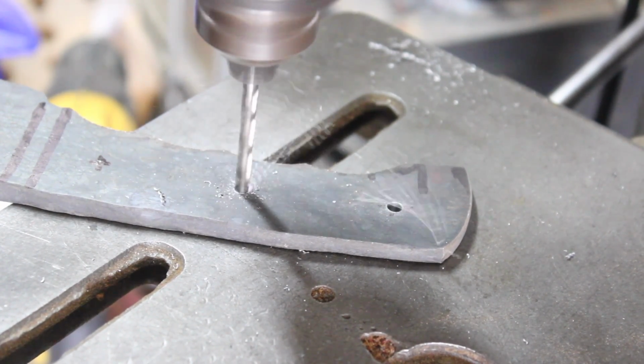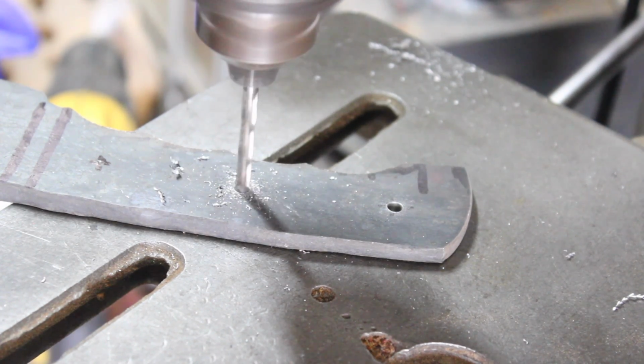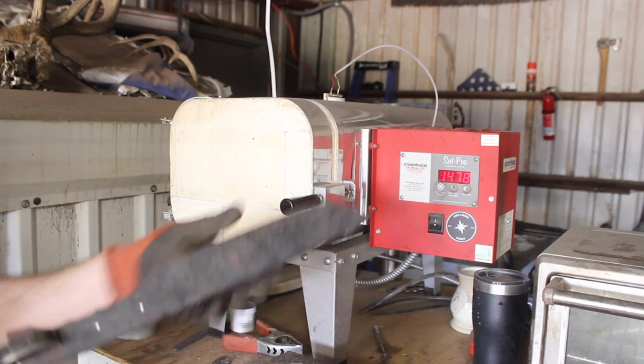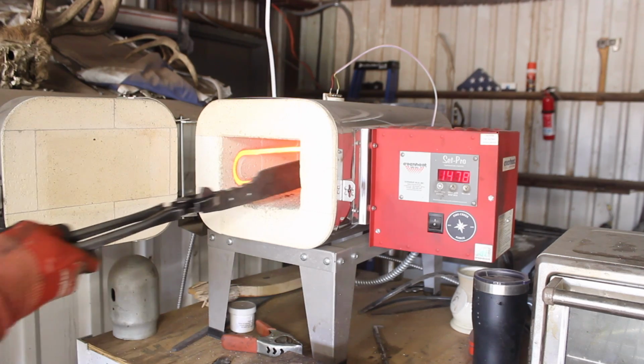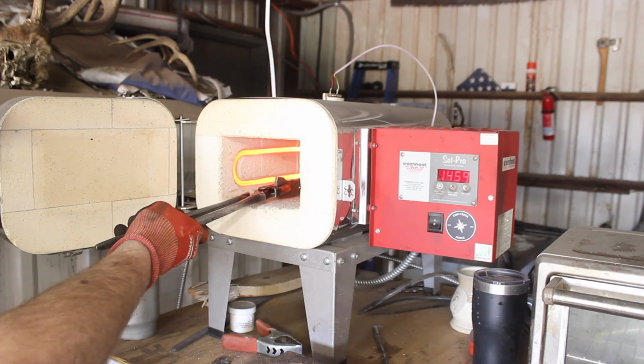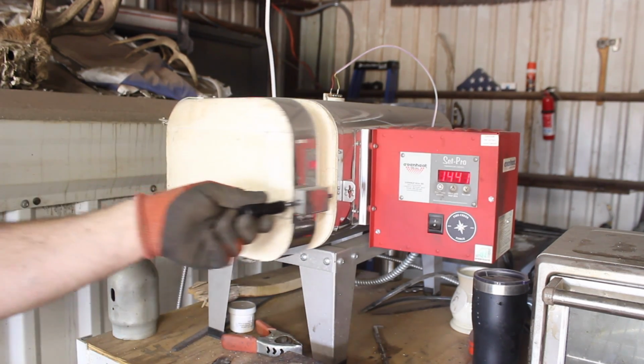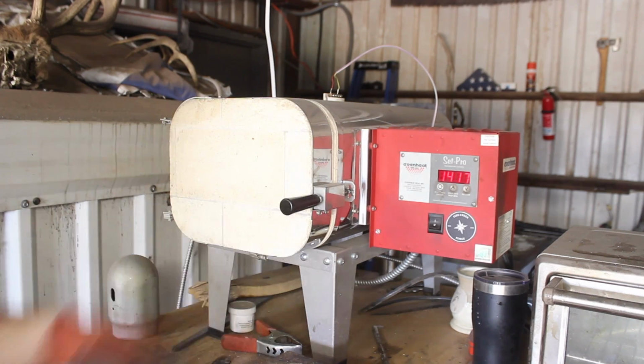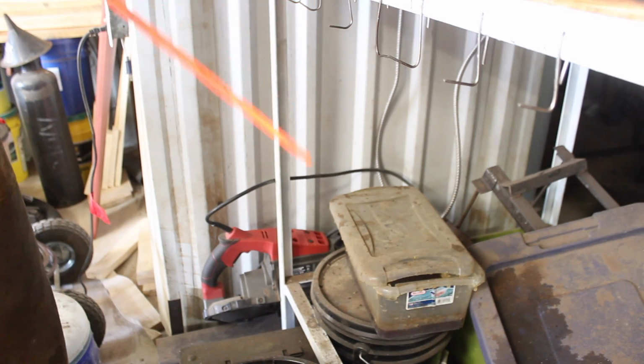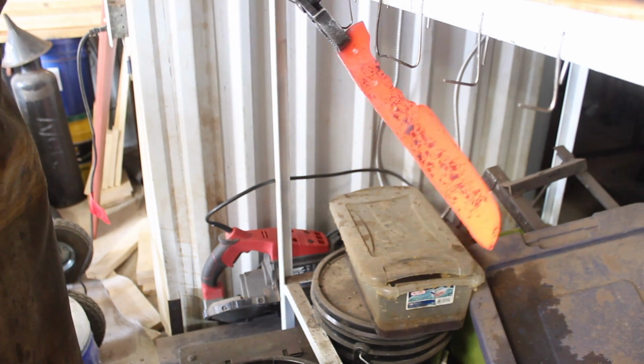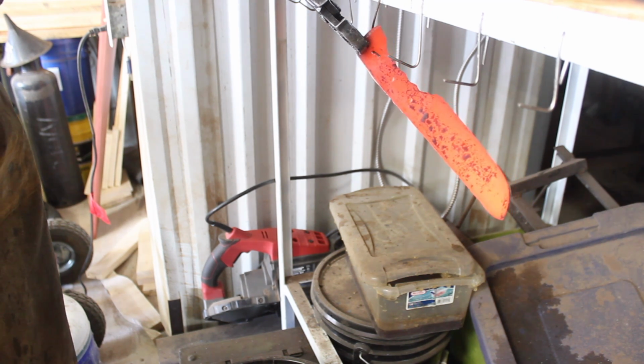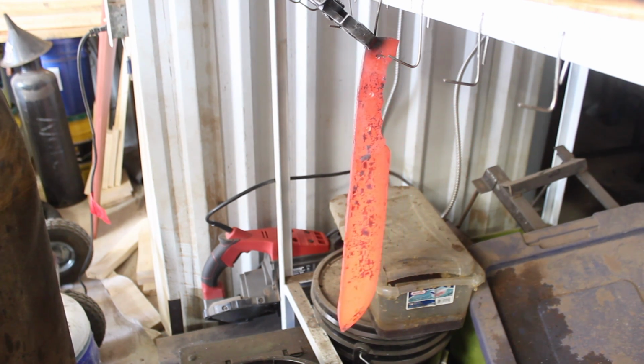Now we can go ahead and begin our normalizing and thermocycling process. The first cycle is at 1600 degrees, and I'll let it soak for about 15 minutes. Take it out, let it air cool in still air. That's going to reset the grain structure, the grain size of the steel, and relieve a lot of stress that we've created in the forging process.